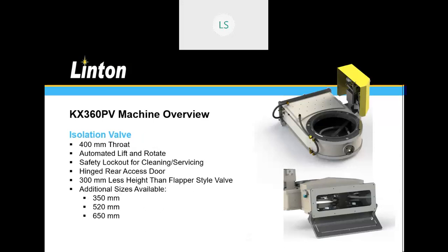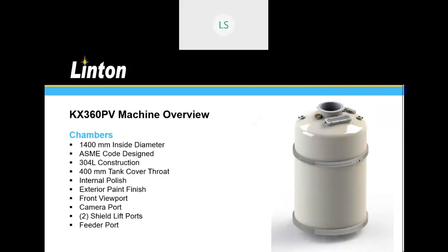We use a pendulum style isolation valve, and what this allows you to do is isolate the receiving chamber from the tanks. So if you have hot molten lava in a tank, pull the crystal, close the valve, and put what's called a torpedo, or a quartz tube filled with additional silicon, into the receiving chamber, close the machine up, open up the valve, drop the additional silicon into the already hot pot, and turn and cool off the machine and restart it up again, which is where it uses your most power. So you can consistently refill the crucible as long as it lasts and pull additional ingots out using this isolation valve.